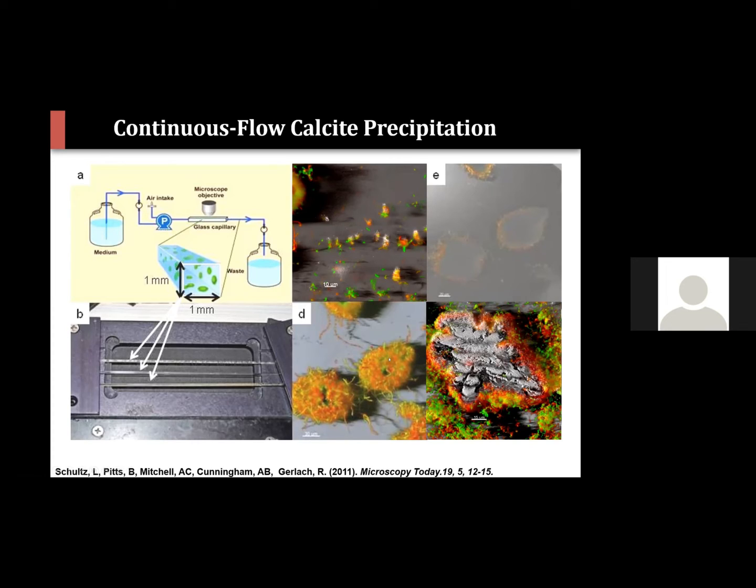So what we see here, for example, is these calcium carbonate crystals encrusted with Sporosarcina pasteurii, but we get continuing carbonate precipitation occurring. So it ultimately seems that the initial direct nucleation on the cell surface occurs, but over time, crystal growth and cell growth continues preferentially on the underlying carbonate to ultimately produce these large carbonate cell masses.